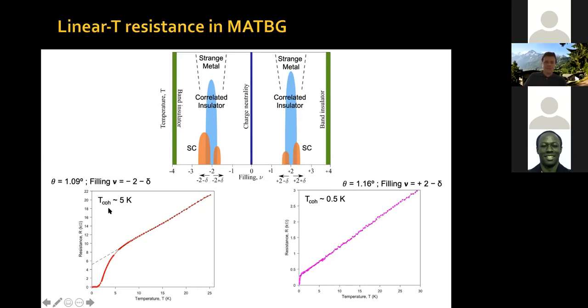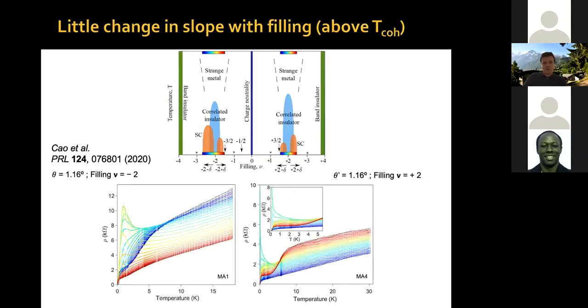Now, I'm saying here T coherence. T coherence is the temperature above which the behavior is linear. T coherence in this case is about 0.5 Kelvin, okay? Because TC is, for this particular dome, about 0.2 Kelvin, something like that. Now, this is something that you can do as a function of density, okay, continuously. So again, it's one of the advantages of our systems.